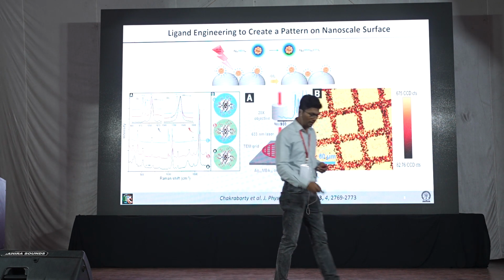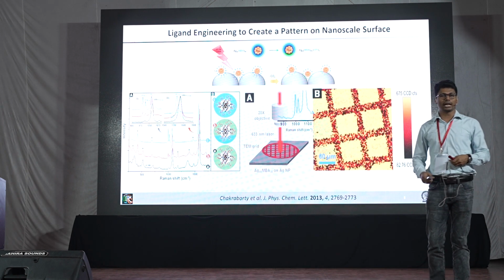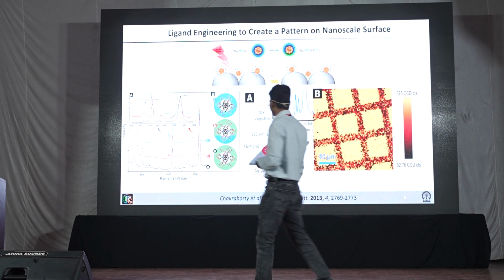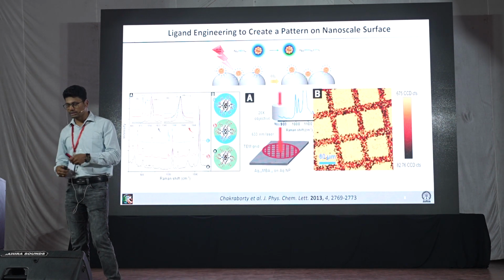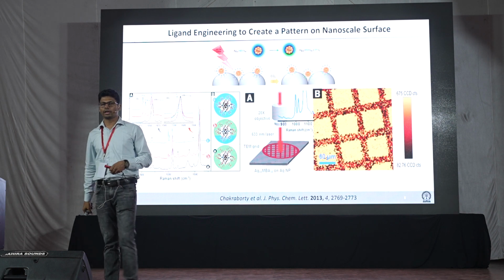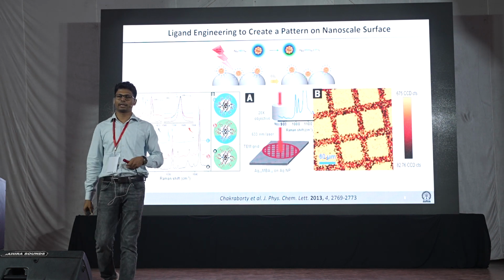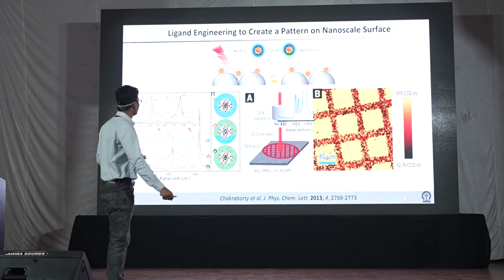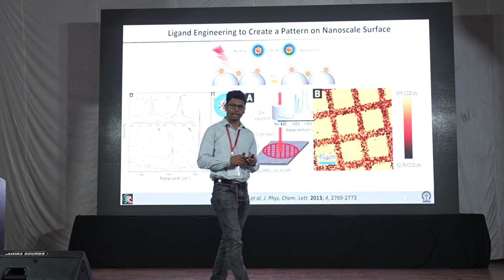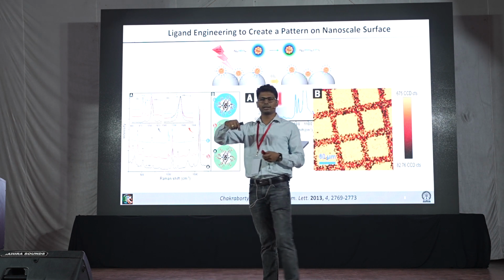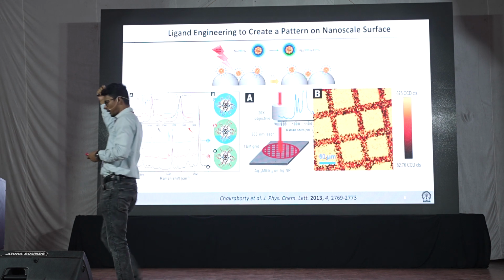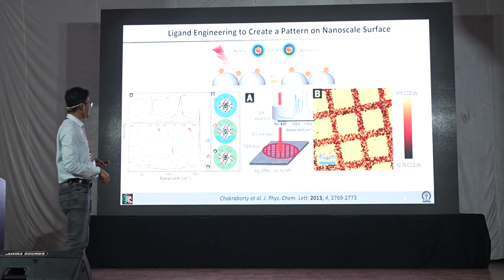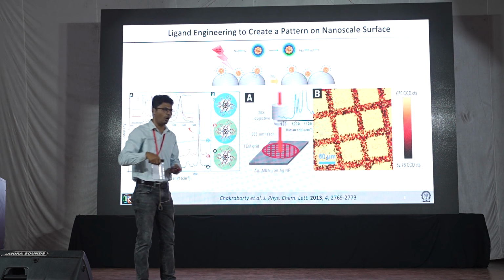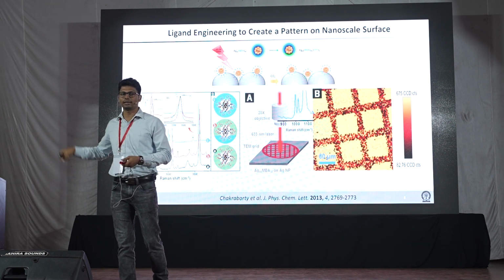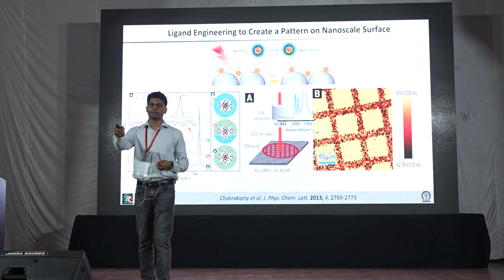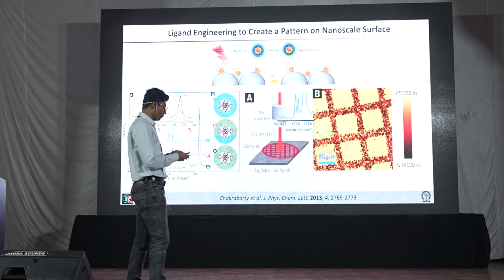Now, what else can we do with ligand engineering? We can do ligand engineering to create a variety of nanoscale surfaces. One example is here: I synthesized Ag44 and then incorporated it on a plasmonic surface, and then we irradiate with the laser. What you see here is that in the presence of laser, the carboxyl part of 4-mercaptobenzoic acid goes away, so basically CO2 is released and you get a phenyl thiol. Since this is happening only in the local region, you can create a pattern out of this, an invisible pattern which you can just see using a Raman microscope. So that is what we try to create.